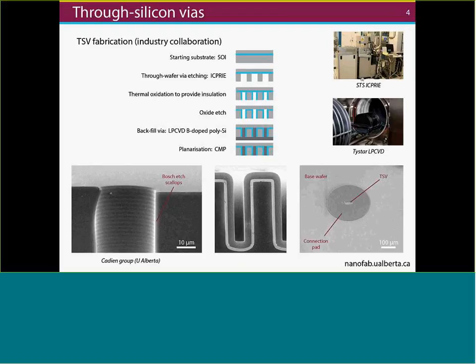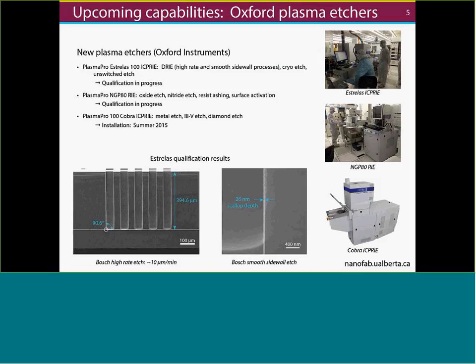So, as I said, while we used this tool for some of the etching tests in this project, we're excited to announce that we are installing 3 new plasma etchers in the near future, which will help to do this type of process or other deep silicon etch processes at NanoFab. This image, it's not a live video feed, but it might as well be, as we've got some of our process specialists who are currently doing qualification on our plasma Estrelas from Oxford. This is a recent example, so we were able to go about 4/5 of the way through a wafer in about 40 minutes. You can even go through if you have larger features.